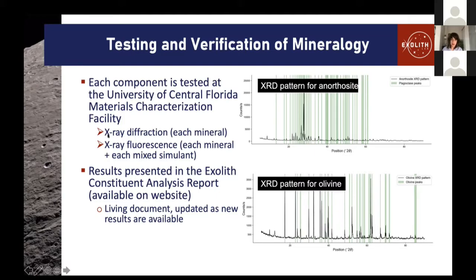We can do that in-house at the University of Central Florida. There's a materials characterization facility where we can get X-ray diffraction and X-ray fluorescence data for each mineral that we bring in. The combination of those is a very powerful tool for assessing the composition of a mineral. The X-ray diffraction gives you a characteristic spectrum that's really a fingerprint for the crystal structure of any particular mineral. The position of these peaks will tell you which mineral it is, and combined with the X-ray fluorescence, which tells you about the bulk elemental composition, you can be pretty certain what your mineral is.